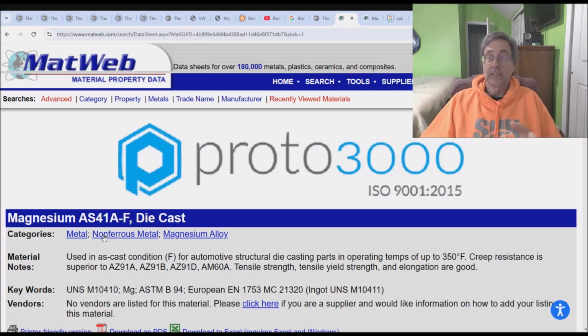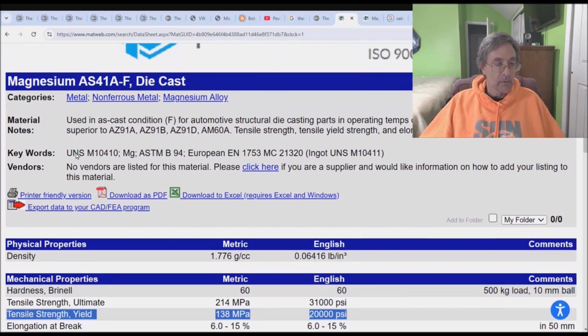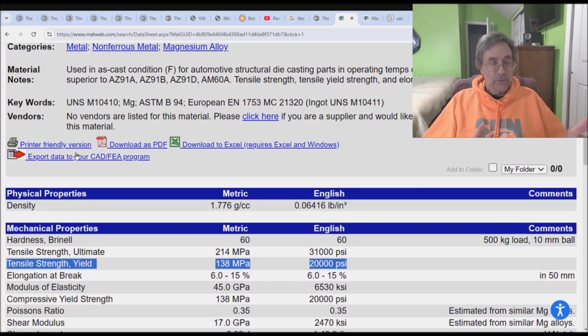What that means is that it encompasses all of the AS41 alloys, A, B, C, D, E, F, all of them. As I said just a second ago, you can vary the sub pieces by a little tiny bit, and you can get subtle changes in the alloys, but the general strength of the alloy and some of the other primary properties don't change. It's an AS41. So what we're looking for is the yield strength. So we come down here and we find yield strength. Tensile yield strength, 20,000 psi.